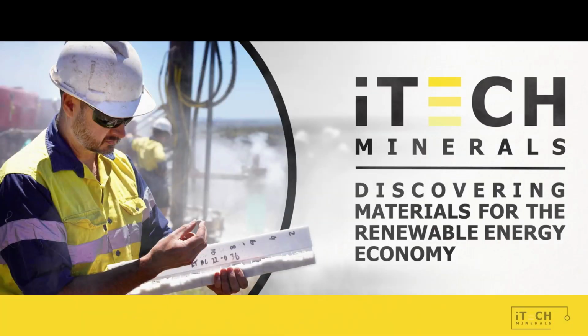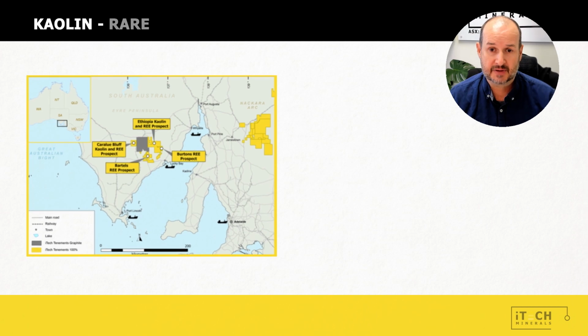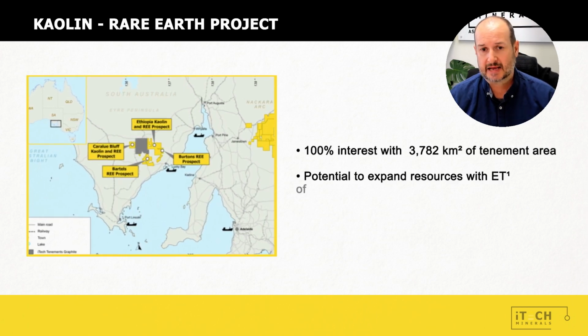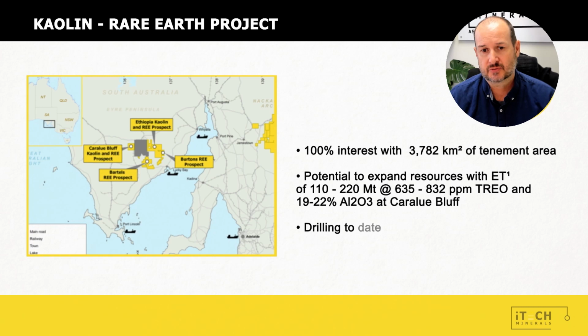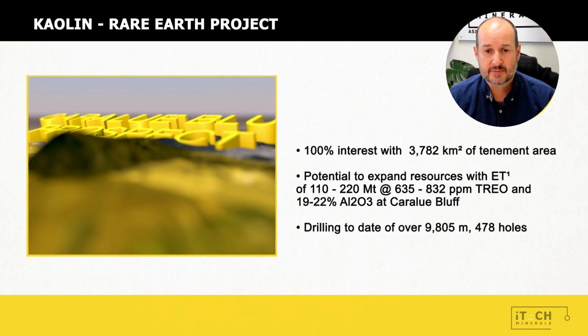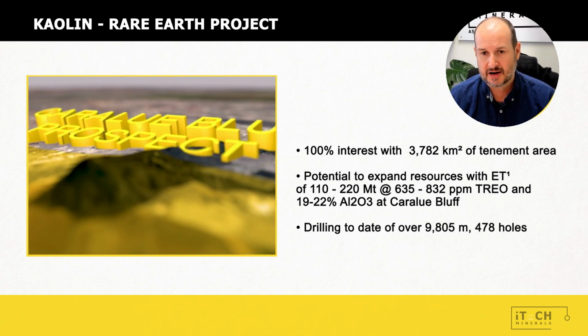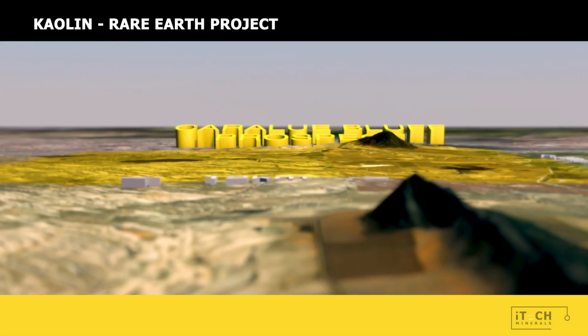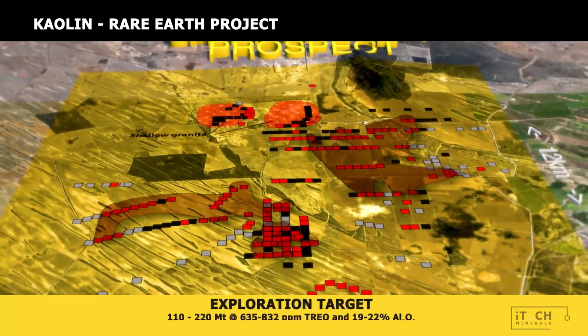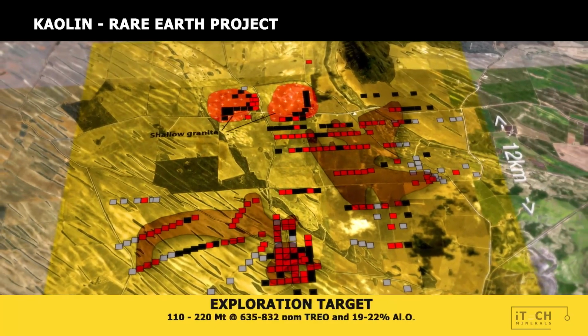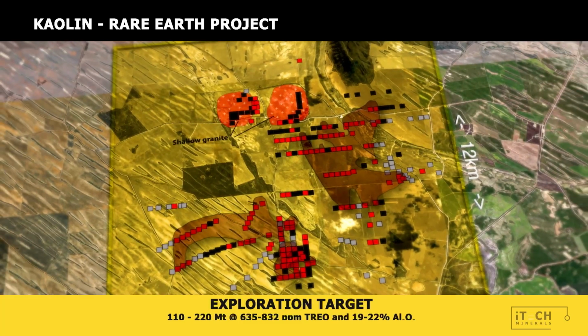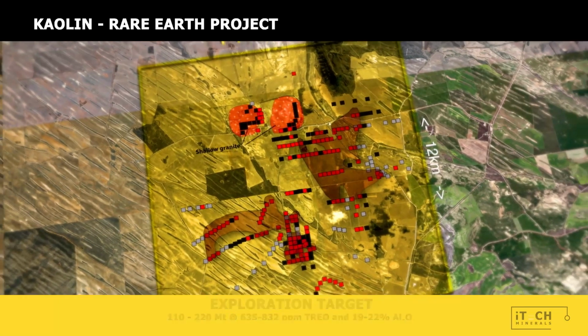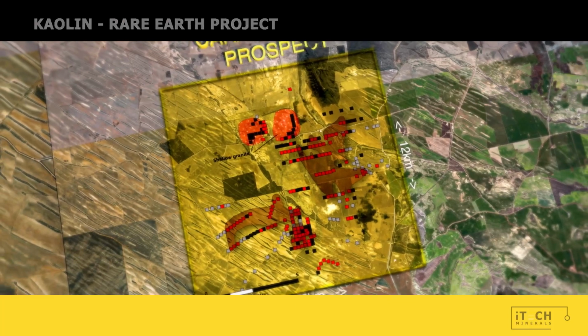Over the past year, since our IPO in October 2021, we've hit the ground running, and we've done a significant drilling program on the Eyre Peninsula, principally exploring for kaolin and rare earth elements that are hosted within that kaolin. We were able to complete a 10,000 metre drilling program and drill nearly 500 holes, and that led us to define a pretty significant exploration target of 110 to 220 million tonnes at between 635 and 832 ppm total rare earth element oxides at CARALUE BLUFF. So we were very pleased with this outcome.